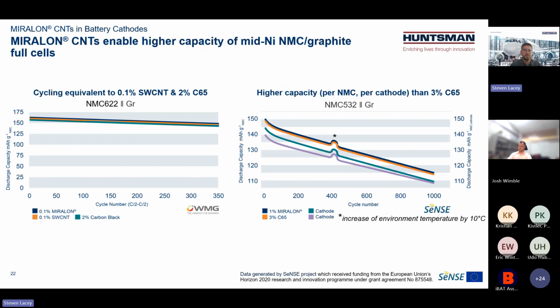From a cyclability perspective, we also saw similar or improved results. So compared to single-walled CNT at a low 0.1% loading or 2% carbon black, we had identical cycling performance in full cells. And when we compared directly to carbon black, we were also pretty similar, using a lot less MIRALON. So you have a higher active content. So when you go per cathode mass, you see in the teal and the purple line a noticeable improvement in capacity at all cycles.